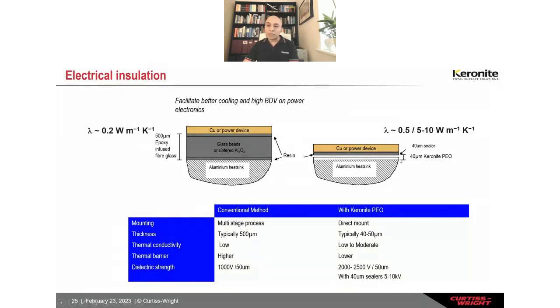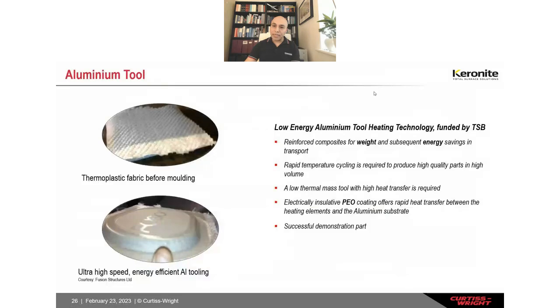But if you want to achieve higher breakdown strength, you can seal those PEO coatings with secondary sealers, for example up to 40 to 50 microns, and achieve 5 to 10 kV breakdown strength, while still having substantially higher thermal conductivity values than the epoxy-infused fiberglass.